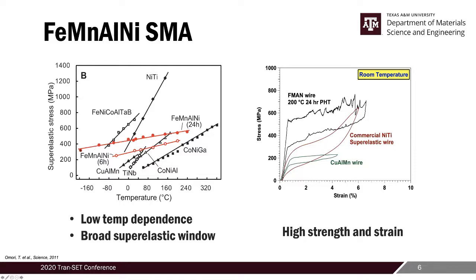And as you can see, as you increase the temperature, the critical stress for superelastic transformation does not increase as much. And this is critical, especially for civil engineering or transportation applications, especially in structures in extreme environments, because once you build your structure, you don't want the property of your material to change due to different temperatures. And this graph shows iron SMAs have higher strength and strain levels compared to the nickel titanium and copper manganese SMAs.